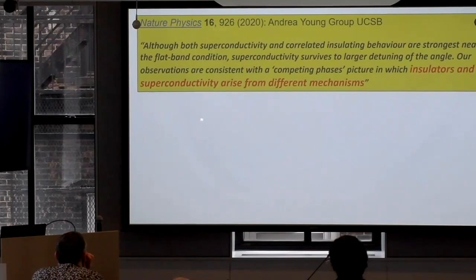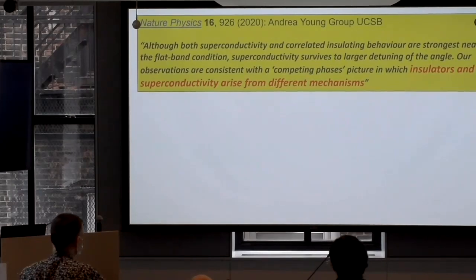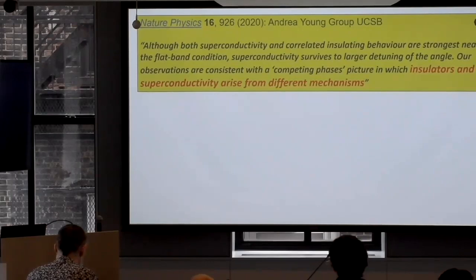Recently, several papers have come out. This is one paper. What they do, they take this graphene and you have gates on two sides. And this was an early suggestion. If you now apply gate potential to increase or decrease screening, you can put the gates very far from each other, or very close to each other, or you can apply an electric field. If it's electron-electron interaction generated, then when you reduce screening, superconductivity should be enhanced. When you increase screening, superconductivity should disappear. Well, exactly the opposite happened.